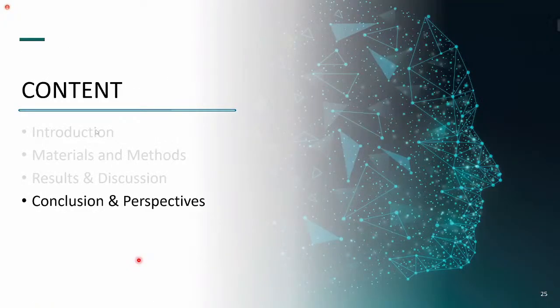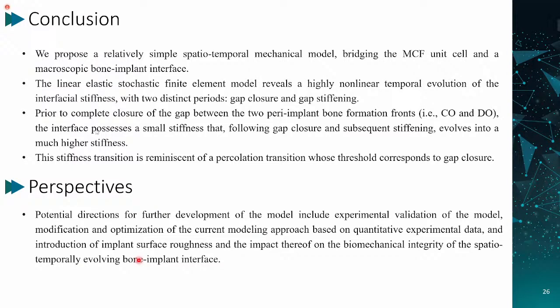So the last, short conclusion and perspective. So in this study, we propose a relatively simple spatial and temporal mechanical model to bridge the MCF unit cell and the macroscopic bone implant interface. The linear elastic stochastic finite element model reveals a highly nonlinear temporal evolution of the interfacial stiffness with two distinct periods, gap closure and gap stiffening. Prior to a complete closure of the gap between the two peri-implant bone formation fronts, the interface possesses small stiffness. Following gap closure, subsequent stiffening evolves into a much higher stiffness. So this stiffness transition is reminiscent of a percolation transition whose threshold corresponds to the gap closure.